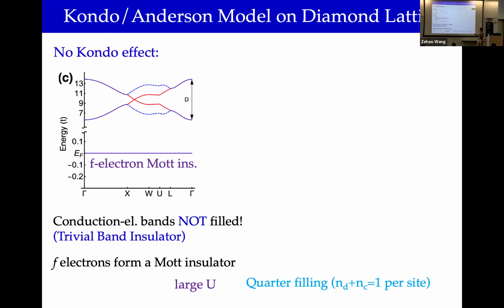So we end up with, from single electron perspective, at low energies, there's no spectral weight at all, nothing. There's basically, in the end, some spins, which are decoupled from conduction electrons. And these conduction electrons could, and they do, have symmetry protected nodes, degeneracies in the band structure, but they're generically very far away from the Fermi energy. So unless you do what Suyan described, just with particular materials design, generically anything like nodes would be sitting very far away from the Fermi energy.